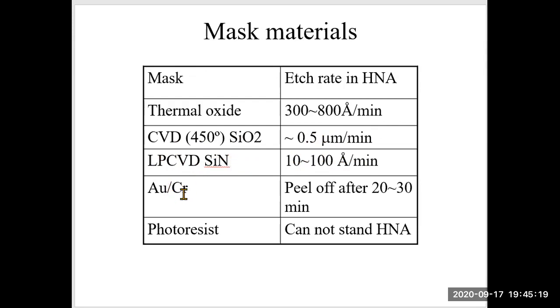Gold chrome thin film will peel off after 20 or 30 minutes in HNA. So if the etch time is less than 20 minutes, gold and chrome thin film can be used as a masking layer. We know that this chrome layer is used as an adhesion layer between gold and the silicon substrate. Gold is inert, so gold will not be attacked by HNA, but the adhesion layer will be attacked. So that's the reason why the gold thin film will peel off.